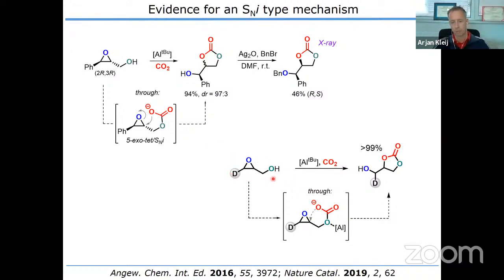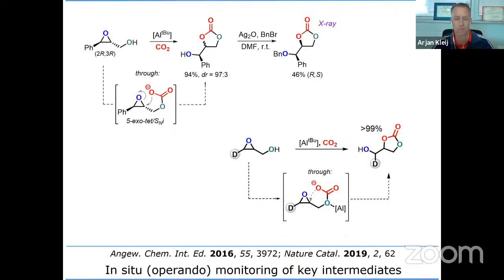Another proof for this mechanism was delivered by this deuterated glycerol. So we have monodeuteration on this carbon of the glycerol. And of course, if we would follow the same mechanistic proposal, we would have to form the glycerol carbonate with the deuterium on the outside of the carbonate cycle. And this is exactly what we see. So we see exclusive formation of this product, and therefore this also supports very nicely the proposed mechanism.